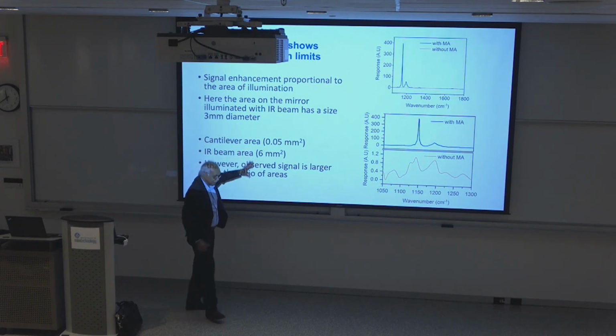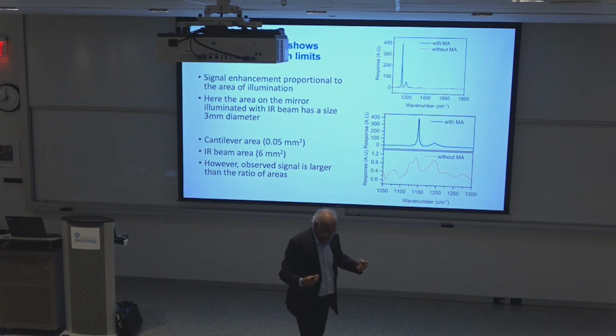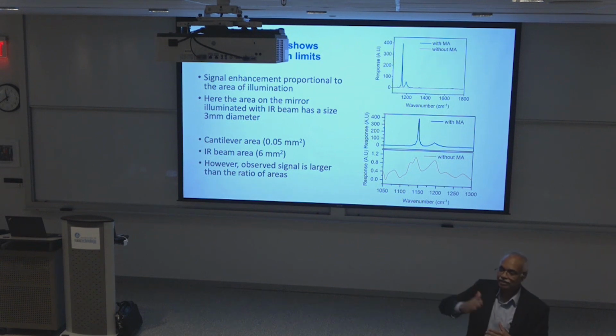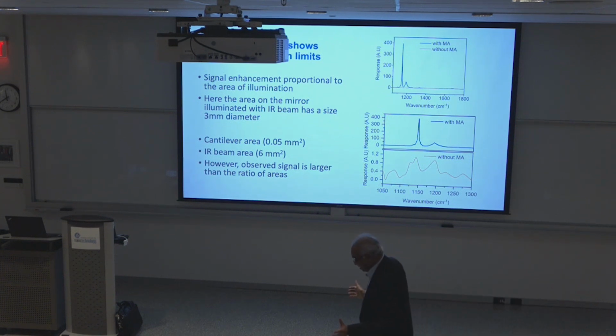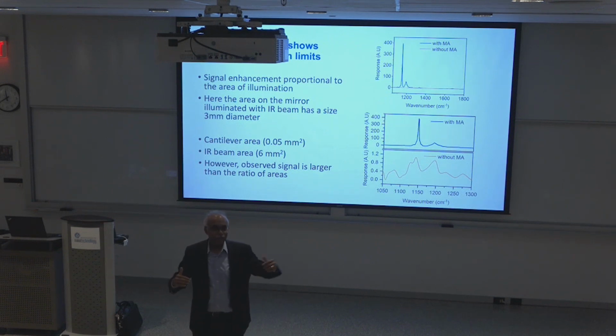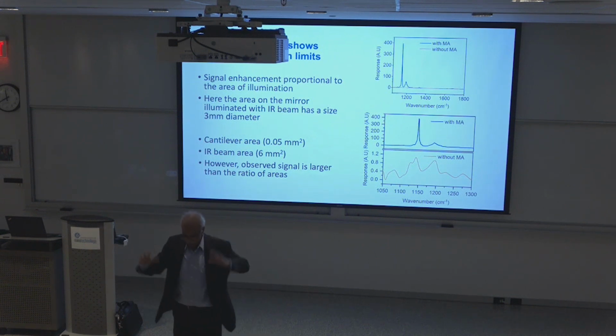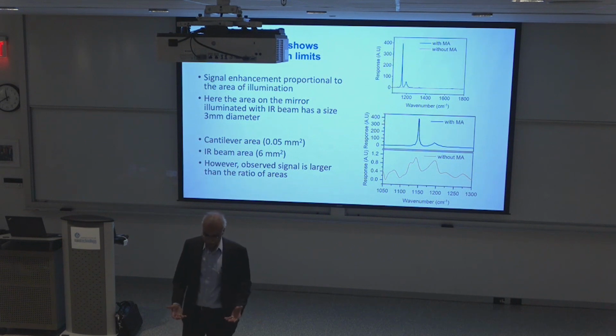If you look at the molecular vibrations, they have vibration and excitation, and the excitation happens within 10 to the power minus 14 seconds, not 10 to the power minus 8 seconds as in optical sensing. So vibrations relax very fast. Maybe I forgot to tell you what happened before the cantilever is bending: when you excite the molecules, they start vibrating and they produce heat, and that's what the cantilever was detecting, right? So there is no coating involved, there is no chemical functionalization, nothing. It's a plain surface, and you excite the molecules, they get excited, they relax, and during the relaxation there is what you call non-radiative heat transfer, non-radiative decay.